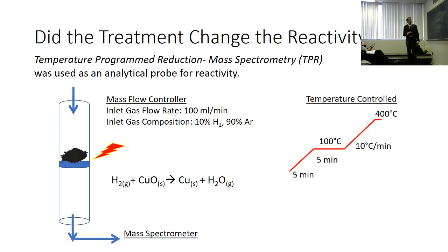So if I'm measuring hydrogen and heating up my reaction, over time, at one point it's going to start reacting with my material. I'll get a dip in the hydrogen signal, and then I'll eat up all my hydrogen and all my oxide material, and then go back to my normal hydrogen level.